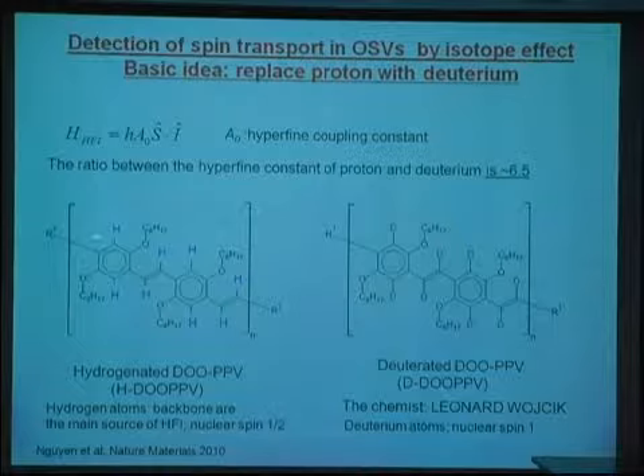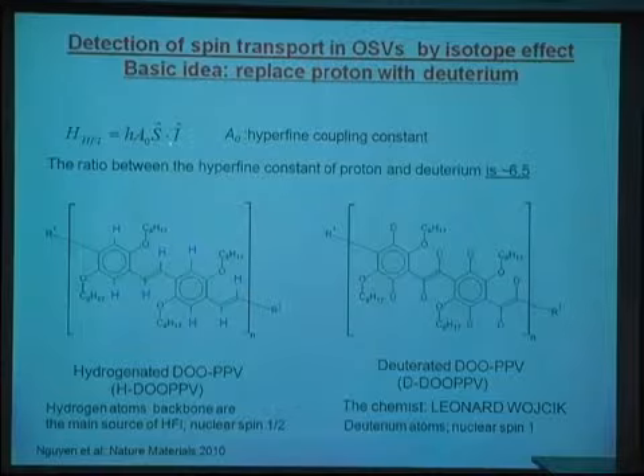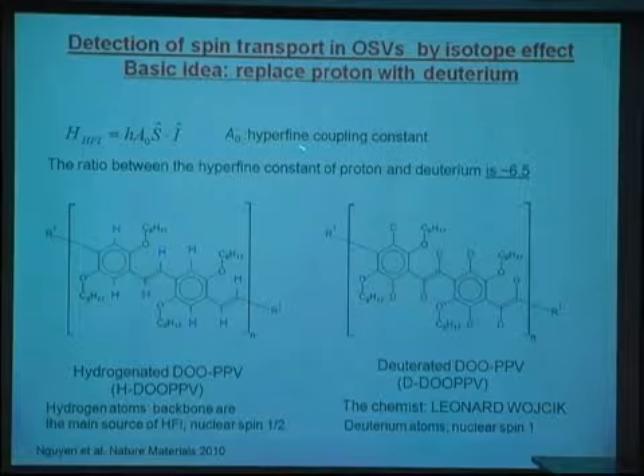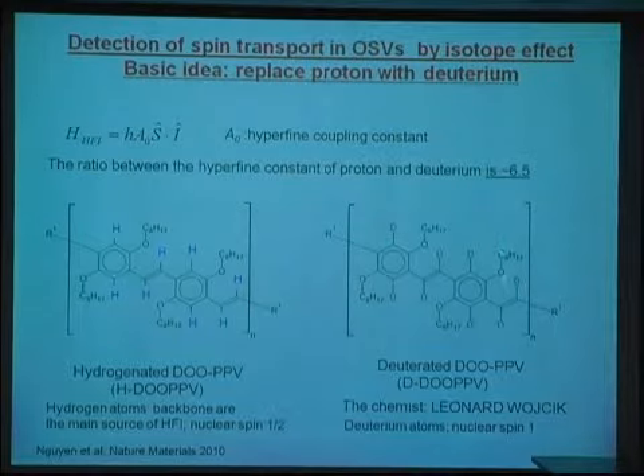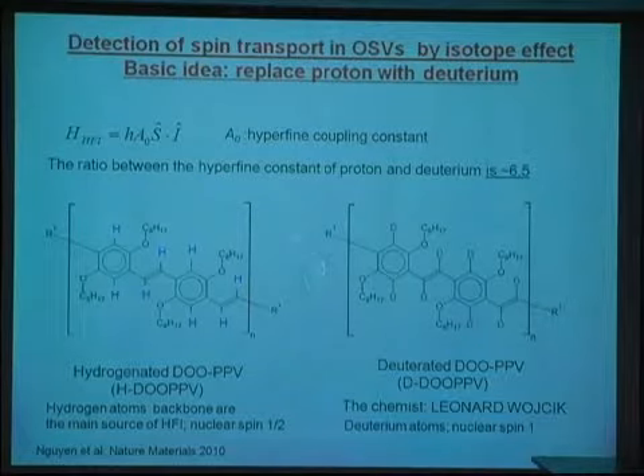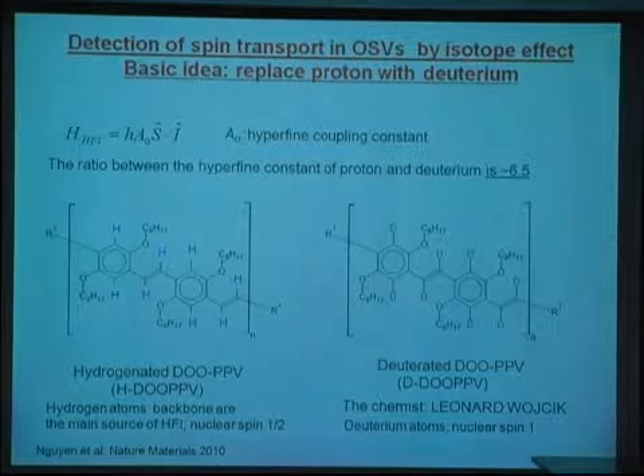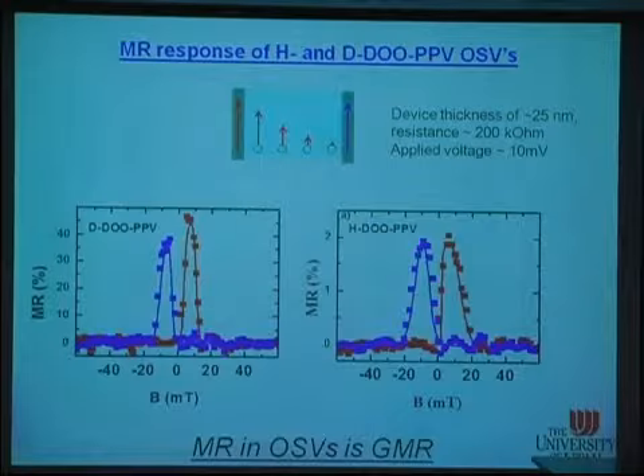So if you look into the hyperfine interaction formula, you will recognize that the hyperfine coupling depends on the hyperfine coupling constant. And the hyperfine coupling constant in hydrogen is about 6 times larger than in deuterium. This leads to the hyperfine interaction of the hydrogenated D-DOO-PPV being about 3 times larger than the deuterated D-DOO-PPV. Okay, and I made devices with those materials.